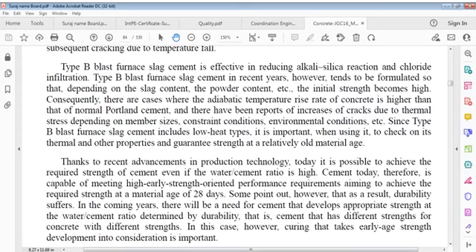So Q equals K times (1 minus e to the power of minus R times (t minus T naught)), where Q is the adiabatic temperature rise at t, degrees Celsius. K is the maximum value of adiabatic temperature rise, degrees Celsius. R is the reaction factor, degrees Celsius per hour. t is age in days. T naught is the starting time of hydration heat. The constant T naught with the highest reliability was determined through regression analysis in section 1.